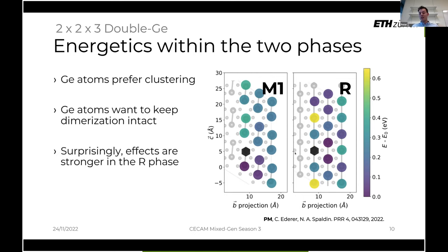And the last, rather surprising thing to note is that these effects seem to be quite a bit larger in the rutile phase than they are in the monoclinic. In the monoclinic, we see the colors to be kind of washed out. You can sparsely make out some structure here, but in the rutile phase, it is really clear which energies are the lowest.